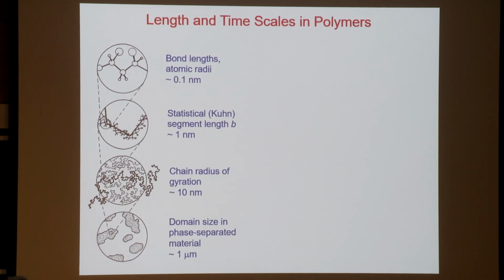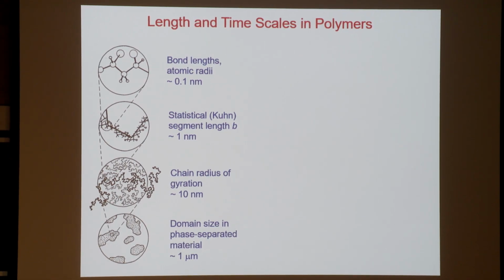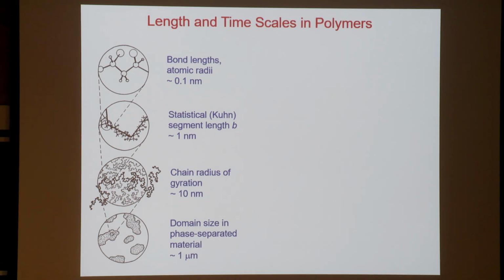So when one tries to capture the properties of polymers and materials in general, one is faced with a serious challenge, namely that these properties are governed by very broad spectra of characteristic times and length scales. If we speak of an amorphous polymer, we have structure at the level of individual bonds and radii, which is typically angstrom. We have structure at the level of the statistical or Kuhn segment length, defined such that the entire chain can be envisioned as a random walk of such segments. For typical flexible polymers, this length scale is on the order of nanometers.